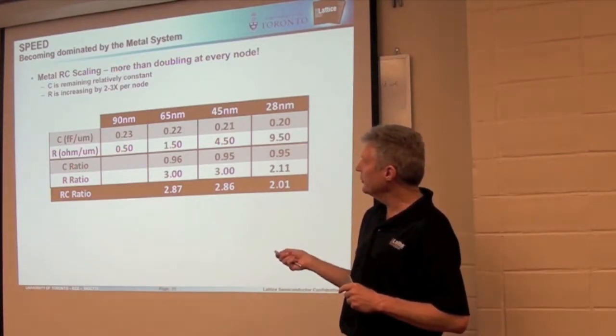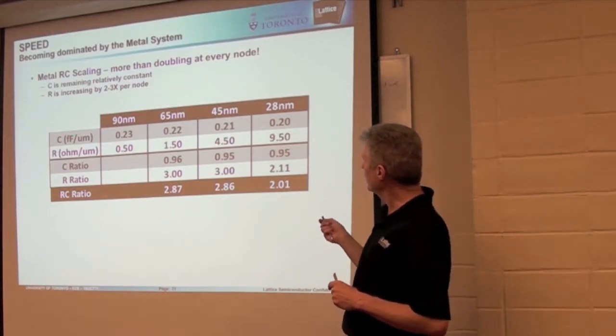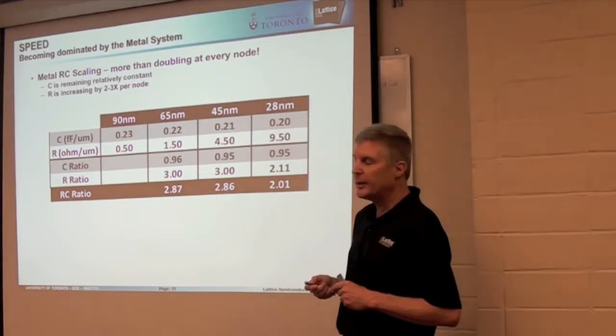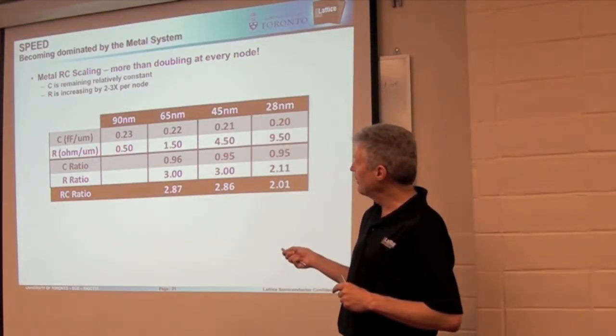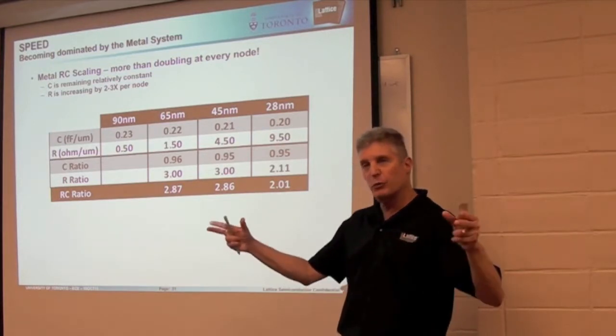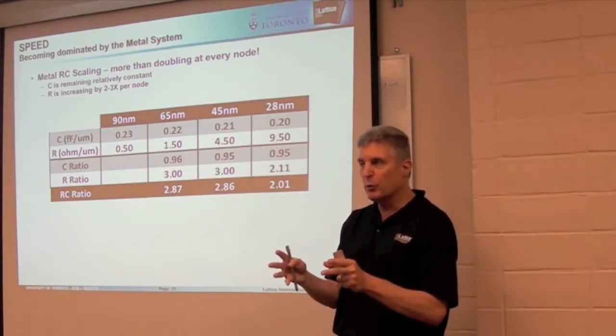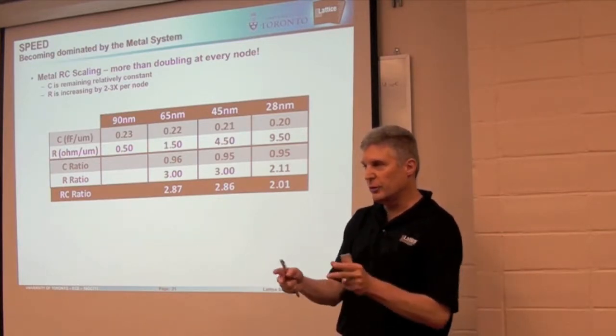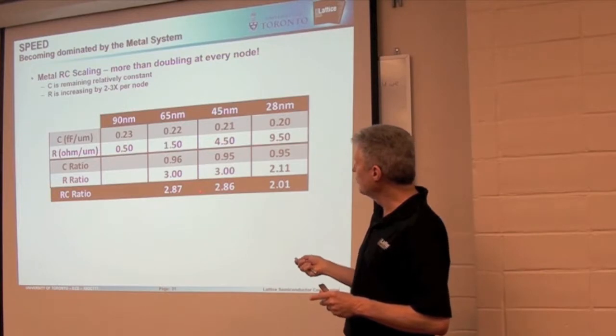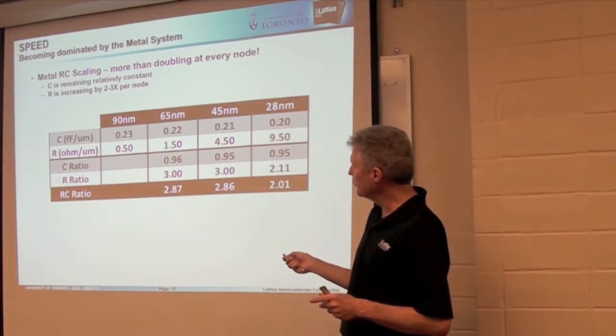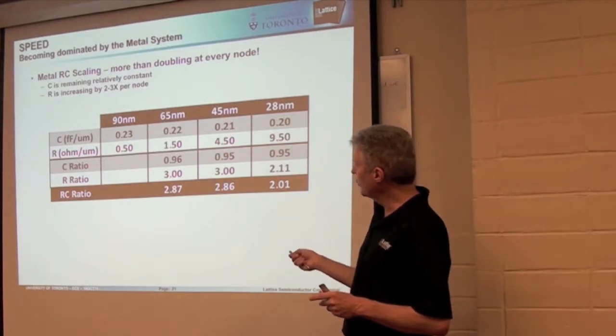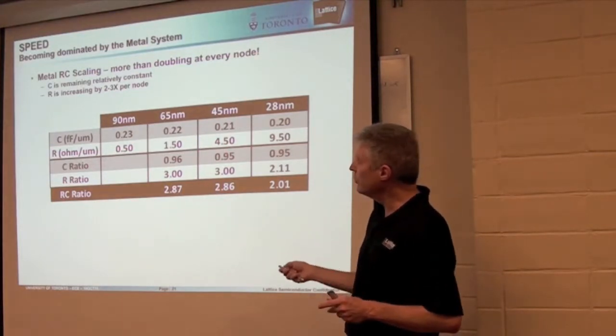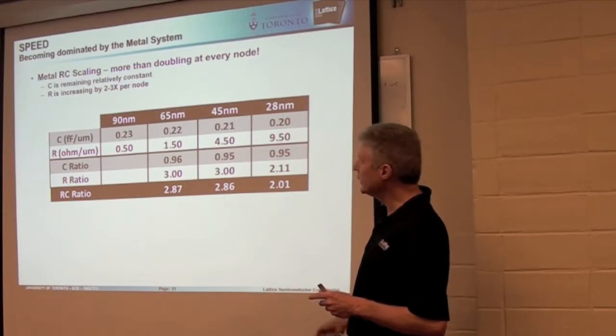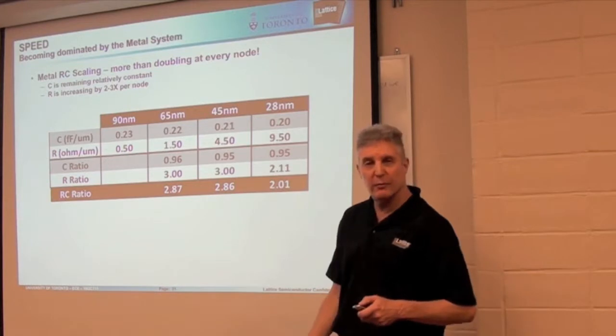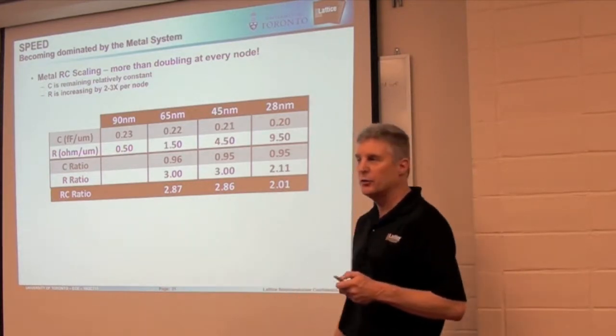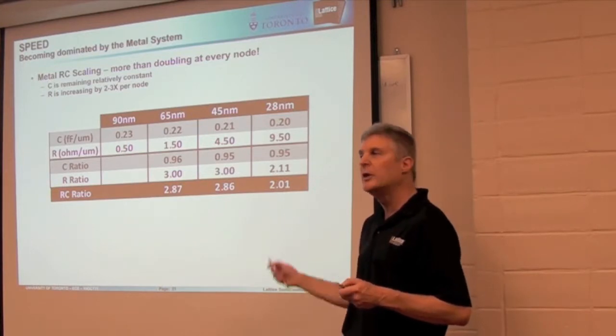Here you can see the capacitance in terms of femtofarads per micron from one technology to the next, and relatively flat over time. The resistance of those metal lines, however, as you can see, is increasing substantially because we are thinning the metal, making it narrower to fit tighter pitches. So the resistance is a function of the width of the metal, and you can see it's more than doubling every node. The ratio from here to here is 3x, from here to here another 3x. So these are the ratios, and the total RC ratio is over 2.8 along the way. At 28 nanometers, we've slowed it down to about 2.0, but nevertheless, your metal is beginning to dominate in terms of the delays. It doesn't matter how fast your transistors are if you can't get through the metal.